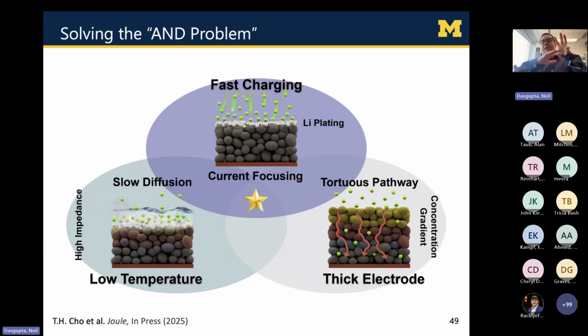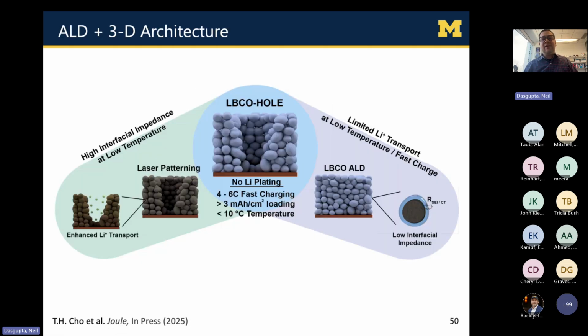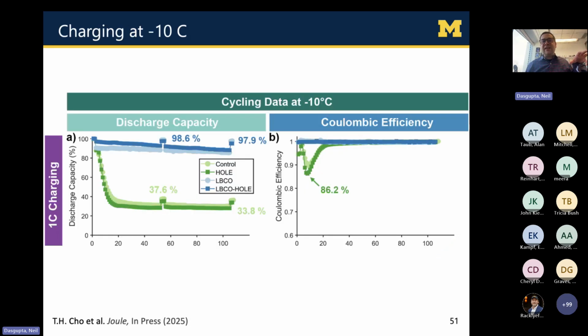So there's kind of this, what we call a trilemma between fast charging and energy density I already talked about, as well as low temperature. And we have a paper that's accepted in the journal Joule that'll be coming out in a couple weeks. We're really excited about this. What we demonstrate is if we combine two of these ideas, the laser patterning plus the ALD surface modification, now not only can we do fast charging at room temperature without lithium plating, but look at these data.